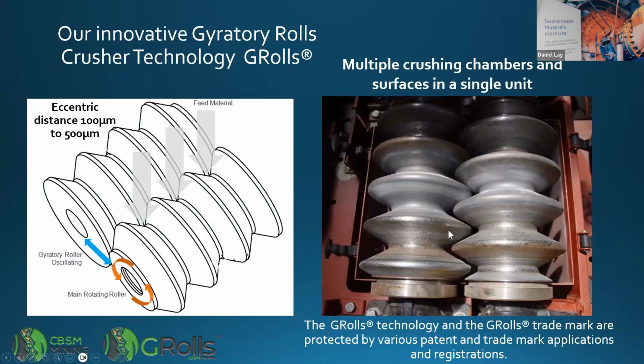Those crushing chambers operate much more efficiently. We have the main roll rotating and dragging material in, but the other roll oscillates or vibrates over a very small distance, so it gyrates and creates pulses, going in and out against the main roller. We've got eccentrics that are 100 micron to 500 micron in size. A normal cone crusher or primary jaw crusher has open size and closed size settings of inches and that sort of thing. Because we're targeting the very fine sizes, we've got those very fine eccentrics. And this gyratory roll oscillates at about 1,000 RPM, so it's very, very fast.